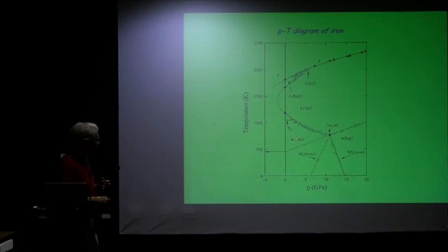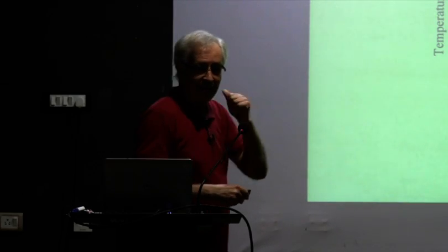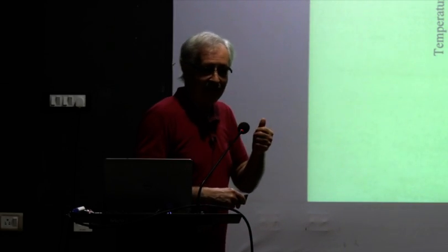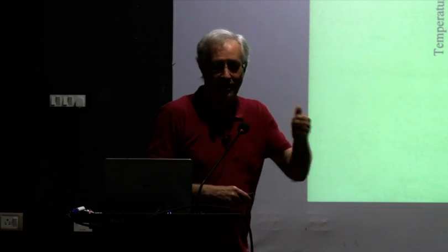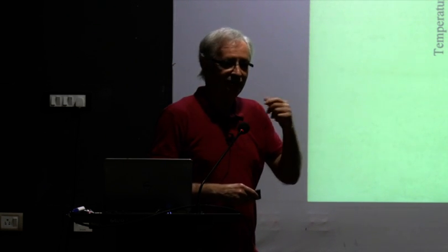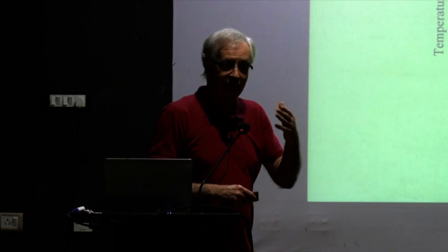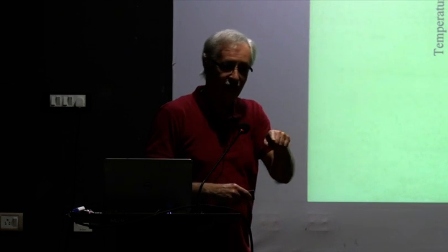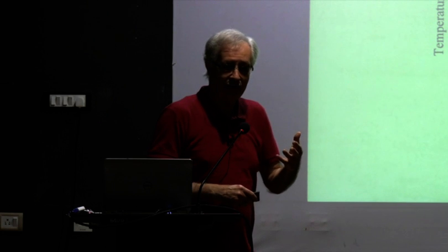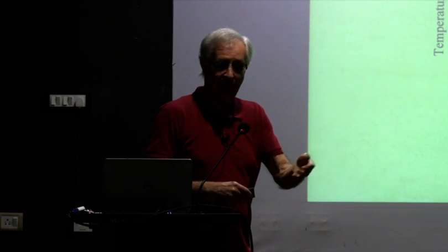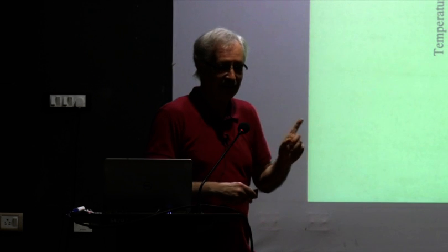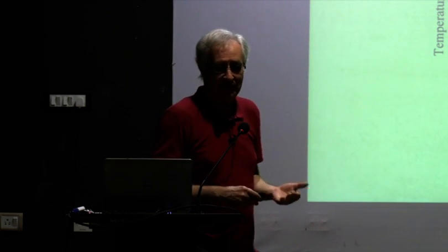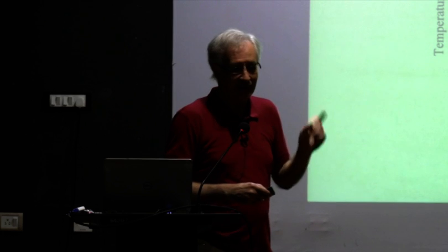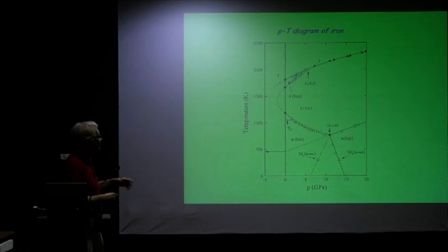Historically, these were designated as alpha, gamma, and delta. There was also a beta phase. The beta phase was the non-magnetic BCC phase historically, because people didn't know. When you come to the Curie temperature and above, when the magnetism vanished, they thought initially that was a new phase, so that was called the beta phase. So that's why beta is missing here. But then it was realized it was the same as the alpha phase, so beta was abolished. So we have alpha, gamma, and delta phases in metallurgical terms.